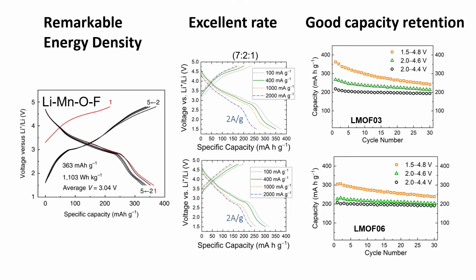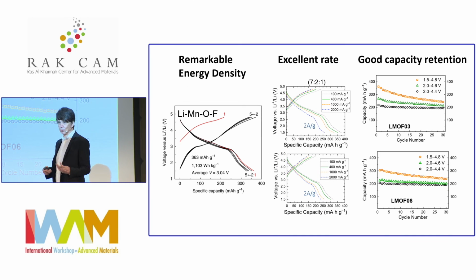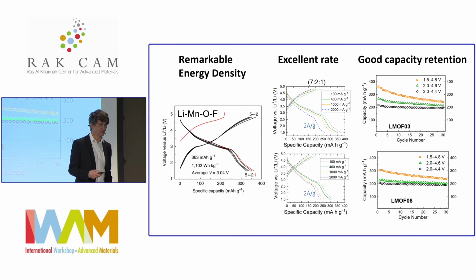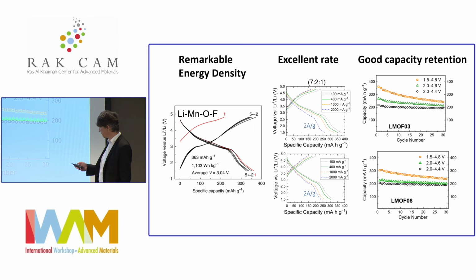But of course, what is the problem with these materials? That we do not know how to make them with scalable synthesis methods, right? Because we make them by heavy ball milling. This is how we can make this large level of disorder. But ball milling is not a way that you're going to make 100,000 kilograms of material. And so this is the challenge now. How do you make these materials with that level of disorder in a more scalable and controlled way?